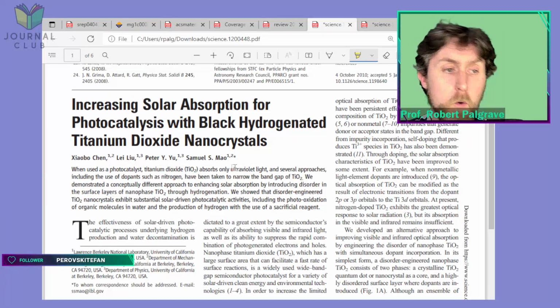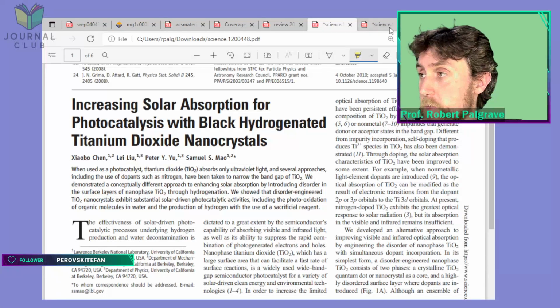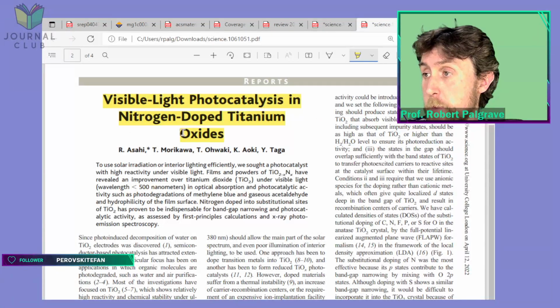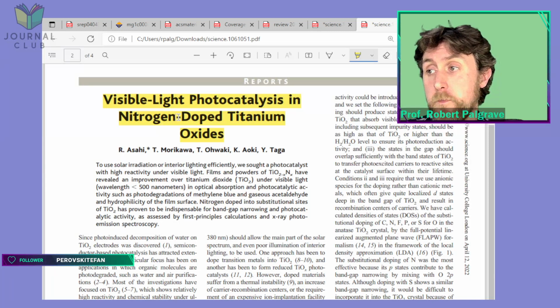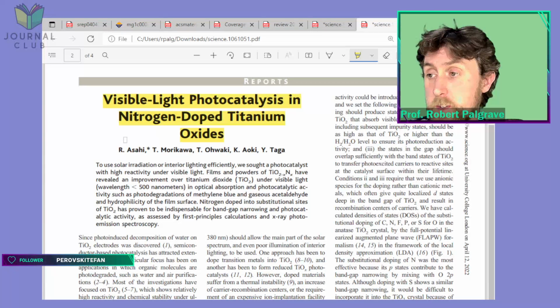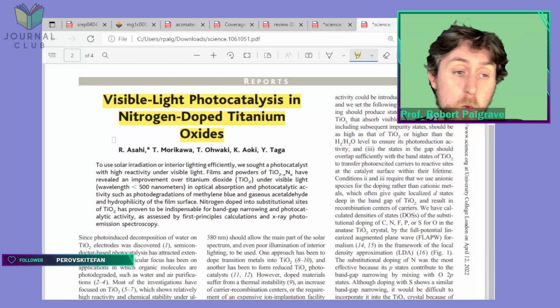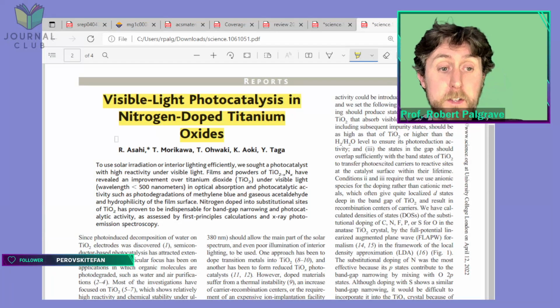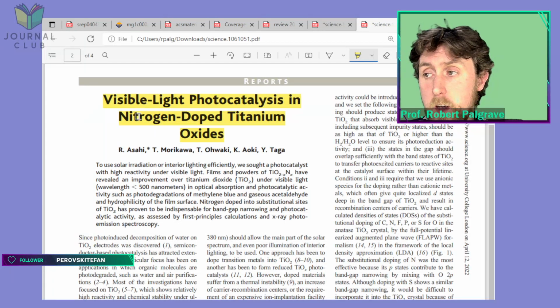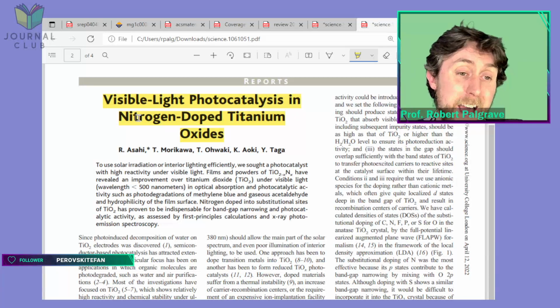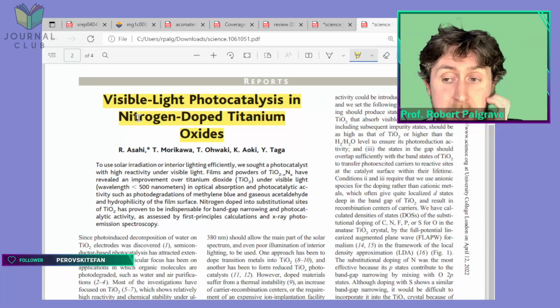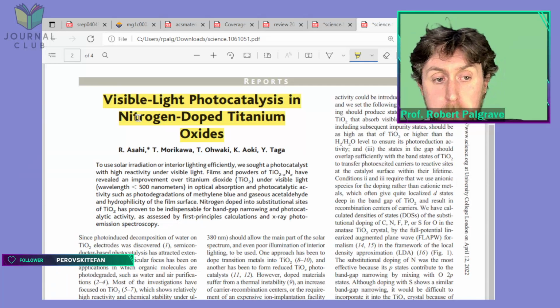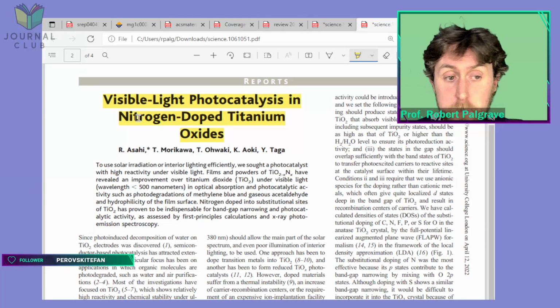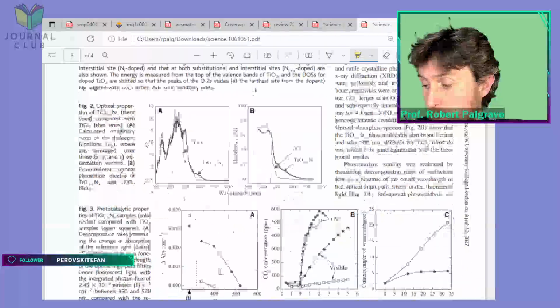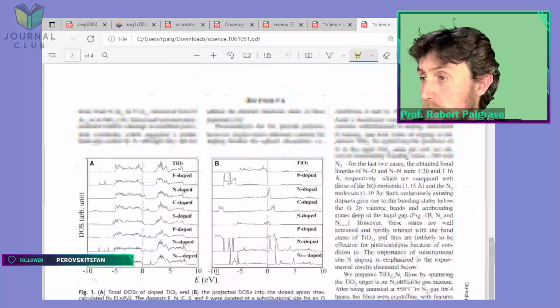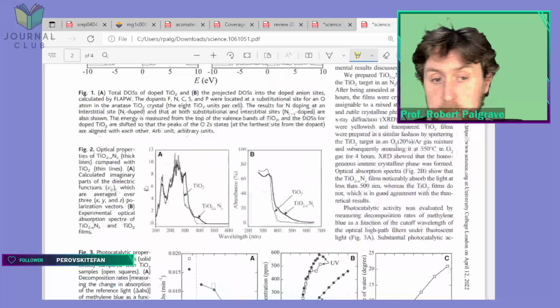So all the way back since 2001, in this very famous paper on nitrogen doping TiO2, the reason this paper was of such interest was because here they managed to report a way to make titanium dioxide visible light active. So they managed to dope TiO2, so they add in an extra element, in this case nitrogen, and that element was able to change the way that TiO2 absorbs light, and make it absorb visible light. I think they maybe have some photos.